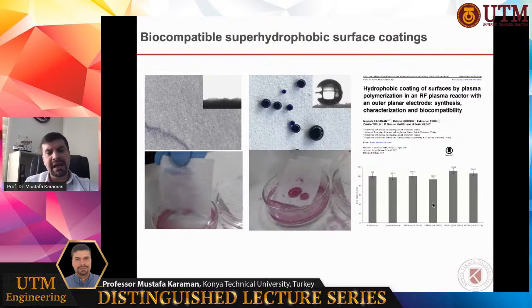The first example is hydrophobic coatings. We usually use textiles and paper as substrates to make their surfaces hydrophobic. As I showed you in the beginning, ICVD usually makes conformal coatings, which is very suitable for textiles. Textile fabrics and fibers are suitable substrates for ICVD. Highly hydrophilic materials can be converted to highly hydrophobic or ultra hydrophobic with the help of CVD in just minutes, seconds. And in that paper, we showed that our coatings are biocompatible also, and they have huge commercial potential.